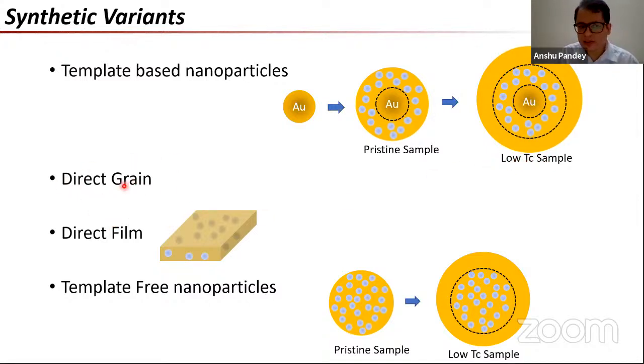We had a few years later also devised a direct grain approach. This is an unreliable approach because this allows you to see strong diamagnetism and even in some cases strong ferromagnetism turning up at ambient conditions. This sort of an approach, however, is not perfectly reproducible. You do the reaction 10 times, and you would probably get it to work once or twice. But at the same time, the important advantage here is that you may take 10 minutes to do 10 attempts once your initial preparations are done. So it's rather fast, but also extremely unreliable in what it does, both in terms of structure and the properties that we observe.